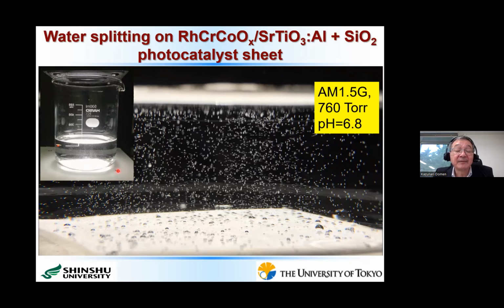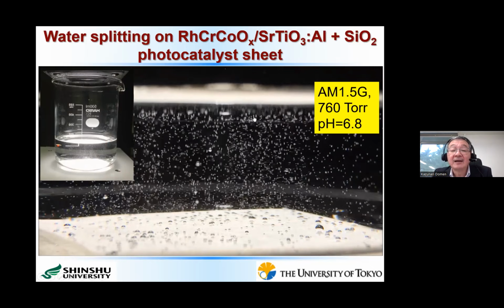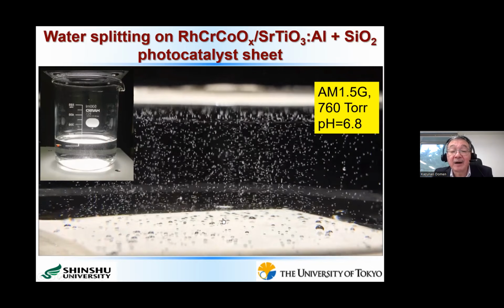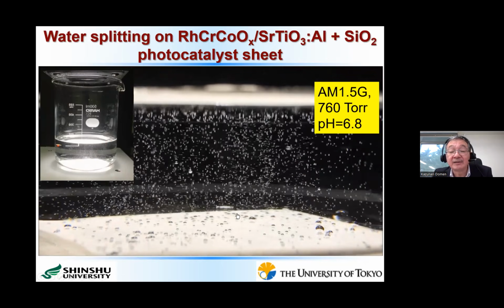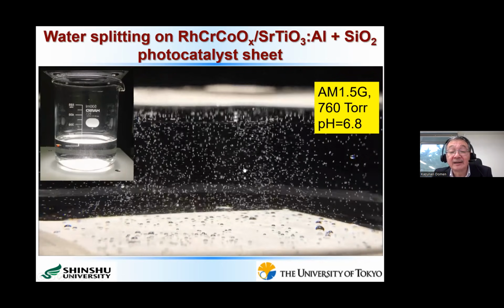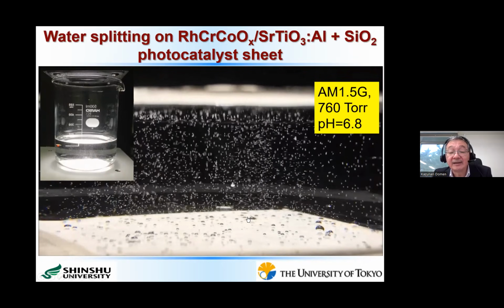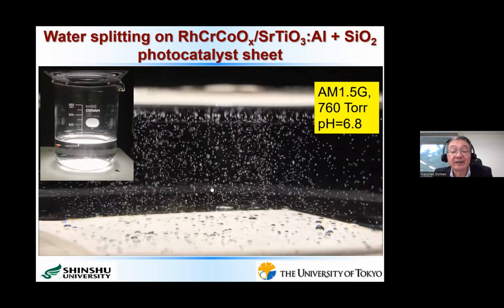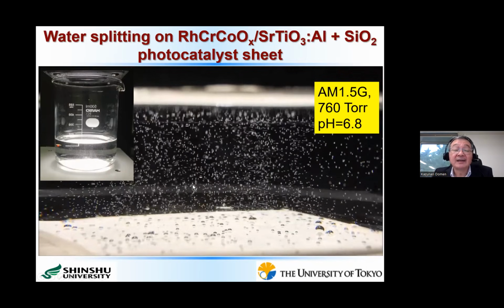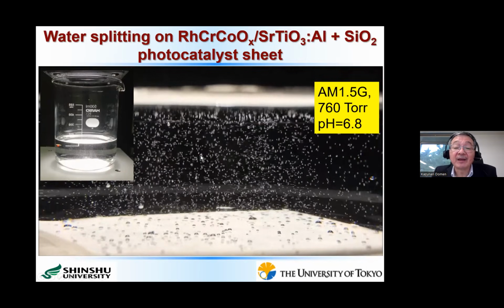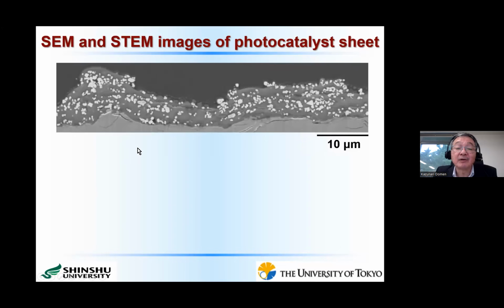This is a 500 milliliter beaker just filled with distilled water. And then, if we put this beaker under sunlight or irradiate with a solar simulator, we can get this kind of bubbles coming out. This is the hydrogen and oxygen, which is evolving using the UV light included in sunlight, like this one. So here I show this photocatalyst sheet in cross-sectional view. As I said, sorry.